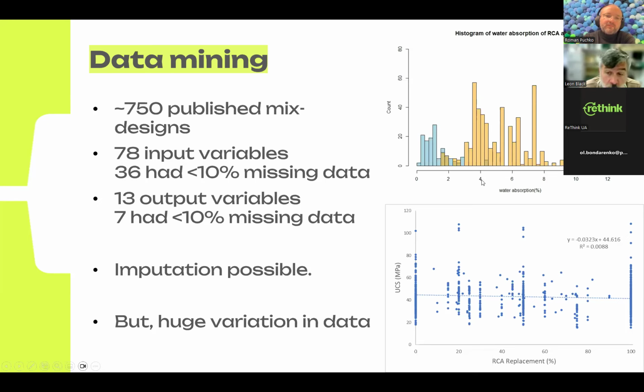This is a histogram of water absorption against the number of mix designs of a given water absorption. Natural aggregates have a low water absorption. Recycled aggregates have a much broader distribution of water absorption. But we can model this with a mathematical distribution, and we can say then that if there is a study that doesn't report the water absorption, we can look at the other properties of this mix and make an informed estimate of what we think the water absorption capacity would be. That's this imputation. Okay, and that was done within input variables.